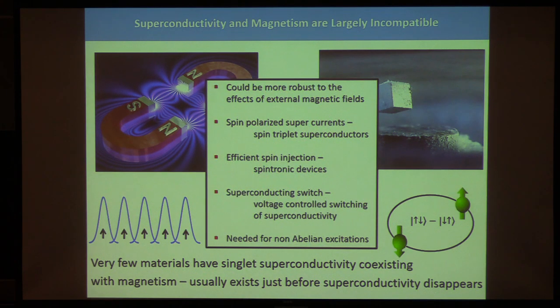So you might ask, well, why would we try to mix these kind of things? And there's actually a good long list of reasons that one might be interested in trying to create superconductors that have a ferromagnetic type of order parameter. One example is, if the pairs of the superconductor were of the same spin, obviously this superconductor will not be as susceptible to magnetic fields as this one. This one really doesn't want magnetic field in it because it will break the pair. Another interesting feature that you could have if you had a triplet superconductor is that you could send supercurrents that carry spin. So that could be really useful. For example, in spintronic devices, if you could send really large densities of spins dissipationlessly, this would be very useful.